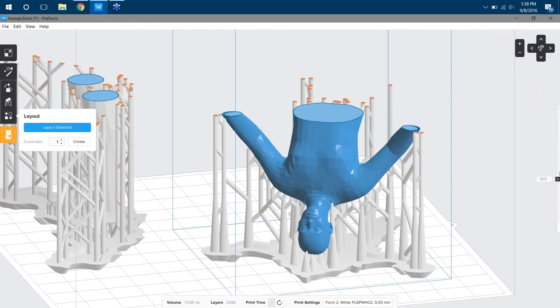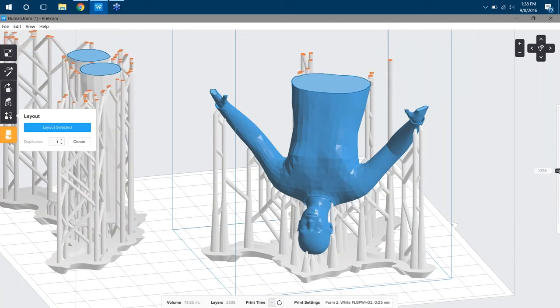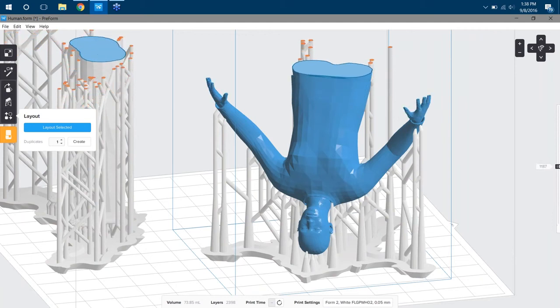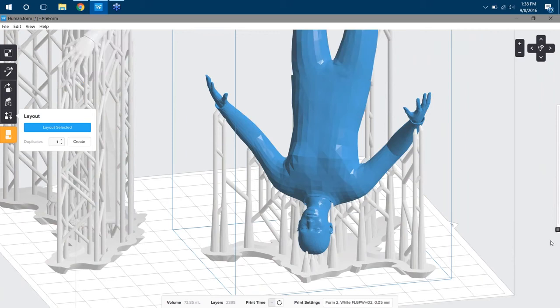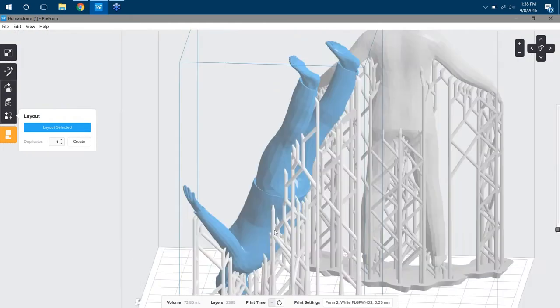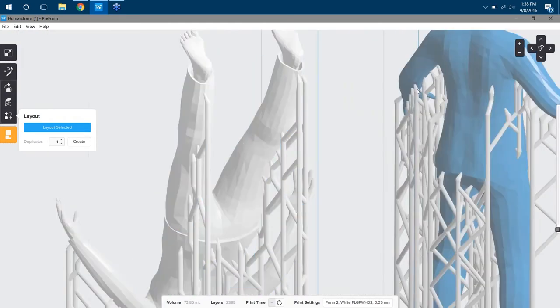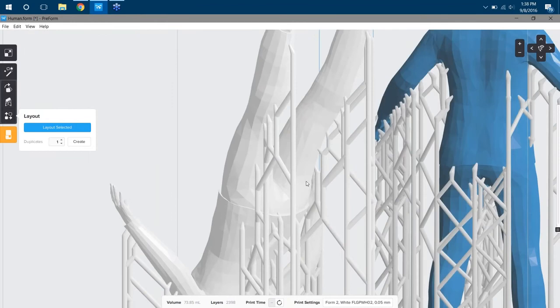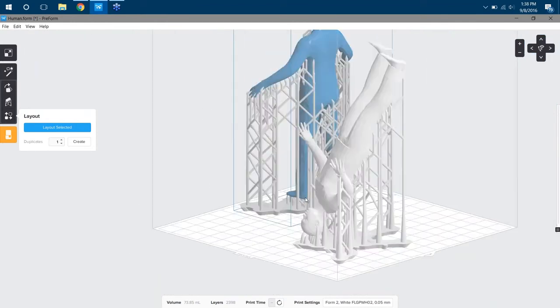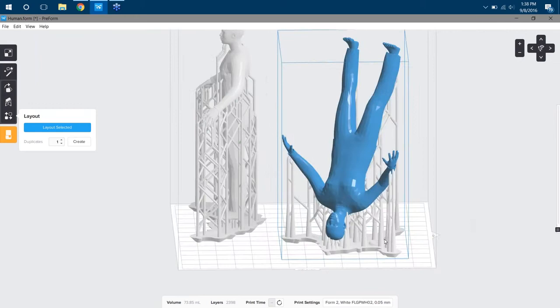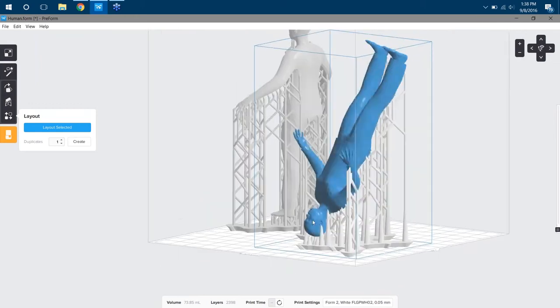But if you angle your model so that when you slice through it, it's a continuous growth, you don't need it anymore. In addition, you also don't have to worry about removing supports from hard-to-reach areas like under his shoulder, like under the armpit or anything like that. Finally, this is just a bit of advice. Whenever you're printing a person, we found the most success to be with somebody who's upside down at like a 30 to 45 degree angle. So let's jump back into the presentation.